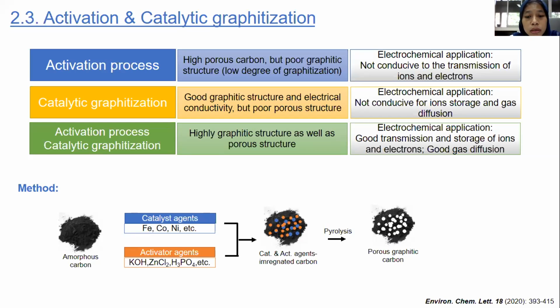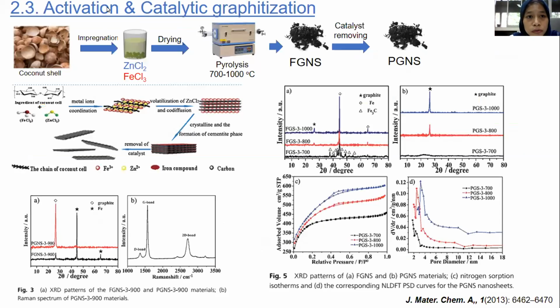Okay, this is an example of the activation and catalytic graphitization method. They use coconut shell as carbon source, zinc chloride as activator agent, and iron trichloride as graphitization catalyst. In a typical synthesis, coconut shell was mixed with zinc chloride and ferric trichloride solution, and the activation and graphitization process of the carbon precursor was carried out at 700 to 1000 degrees Celsius.